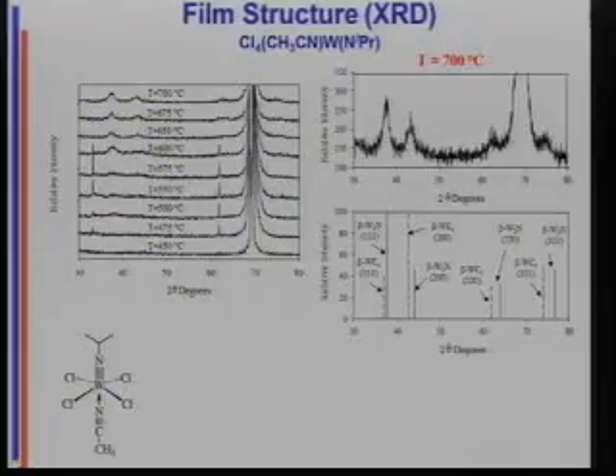Okay, so try the experiment. What do we get? At low temperatures, and yeah, it still kills me to call 450C low temperature, but at low temperature depositions my material is X-ray amorphous. I don't see anything in the XRD. As I grow at higher and higher temperatures, I start to see crystallization. And these peaks are going to allow us to identify the nature of the crystalline material.